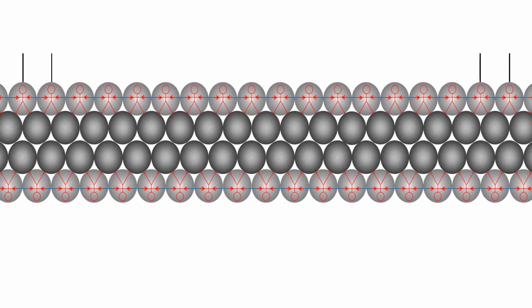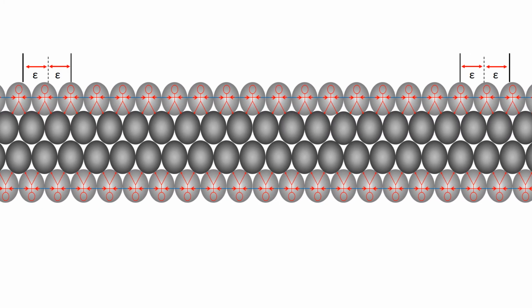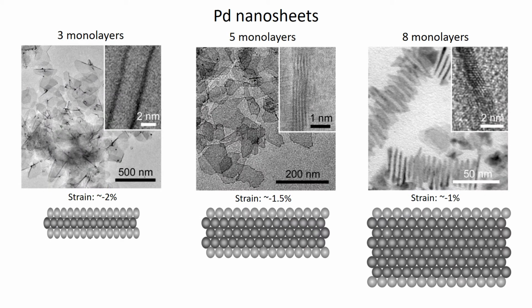If we decrease nanosheet thickness, analogous to using a thinner spring, the magnitude of strain will increase. Based on this strain-thickness relationship, we use density functional theory calculations to design a series of nanosheets. We have synthesized palladium nanosheets, which vary from 3 to 8 monolayers in thickness and have compressive strain from 2%